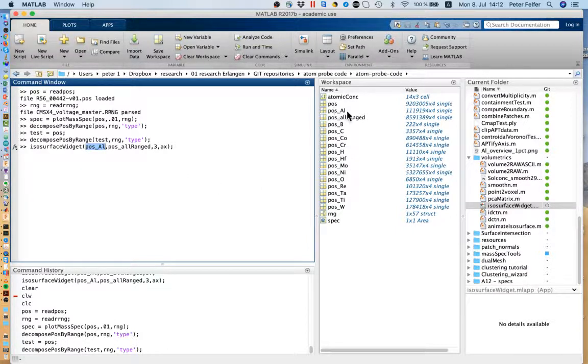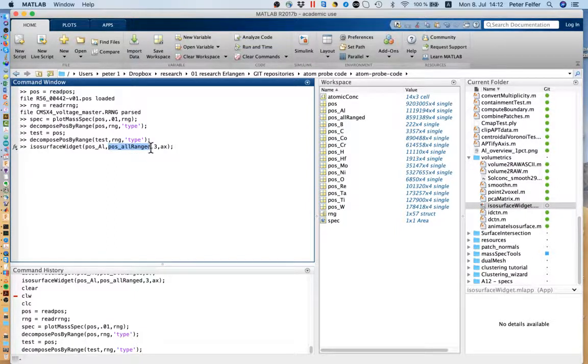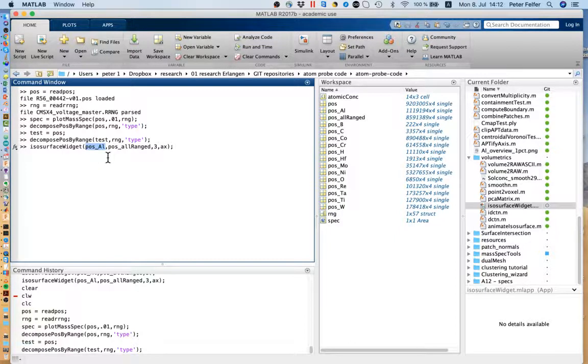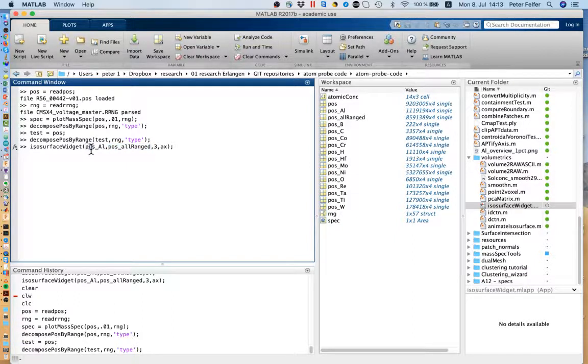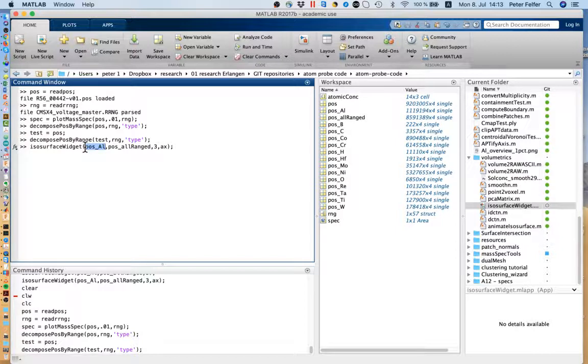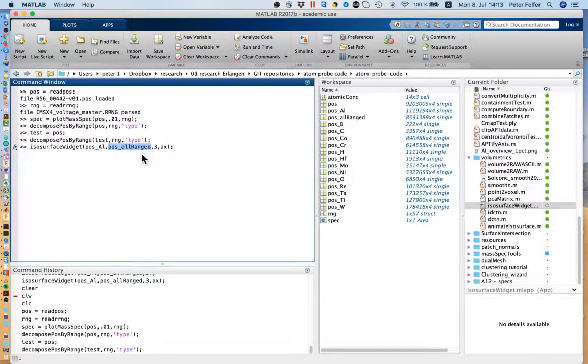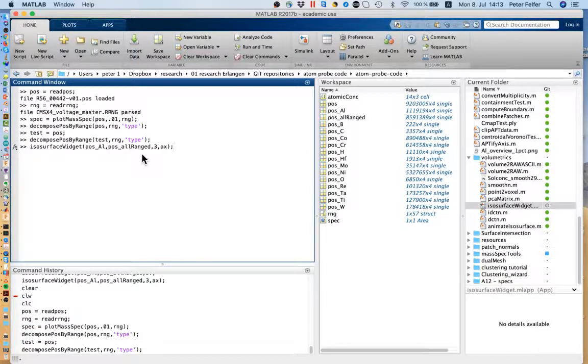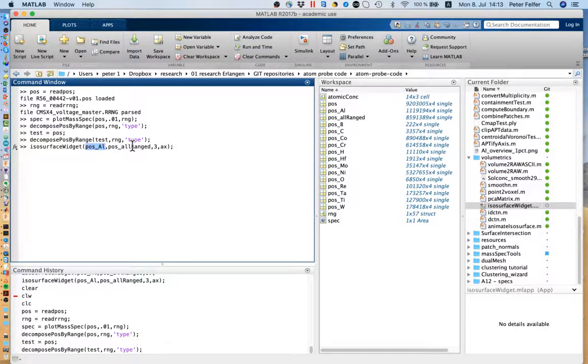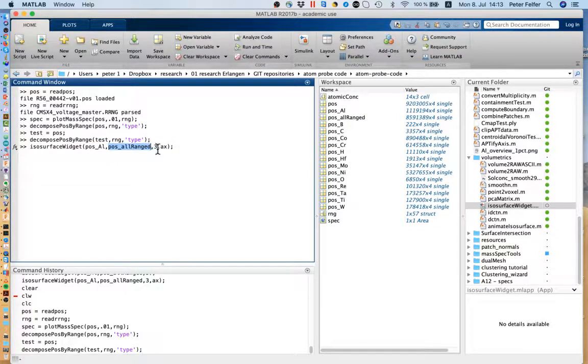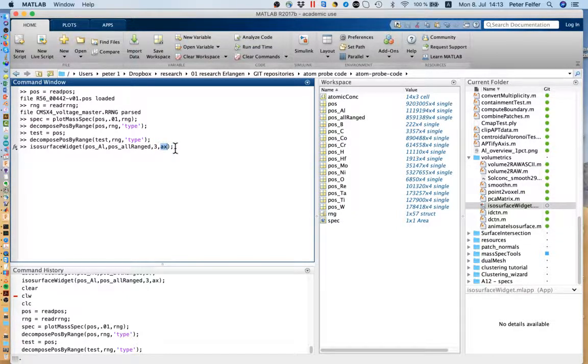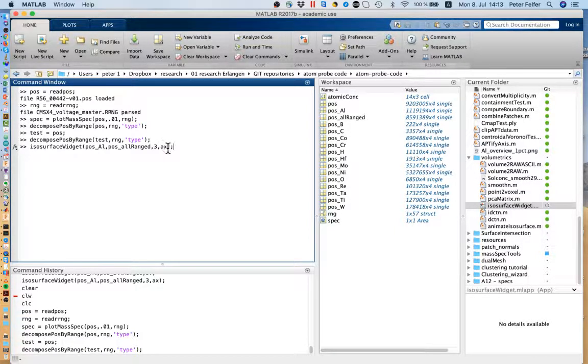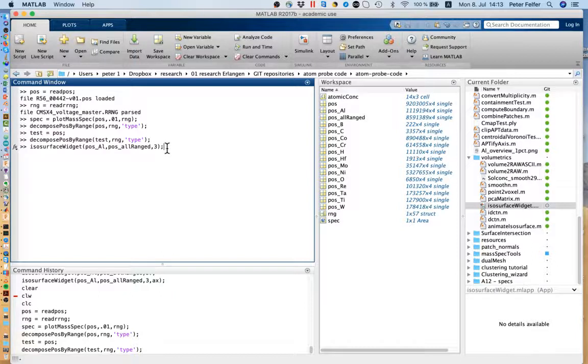Essentially a concentration field is number of atoms of a certain species of interest divided by number of atoms of another species. Or if you want a percentage, you could go, maybe if you want aluminum and nickel, you could go POS aluminum together with POS nickel divided by all range. But maybe you want to have stoichiometry isosurfaces and things like that. So this is the numerator and this is the denominator. Then we have the voxel size in nanometers, they are isotropic voxels. You can also give non-isotropic voxels. Then we have ax, and ax is the axis it will plot it into. For now I don't have one where I want to plot it into, so I can remove that and it will pop up with its own figure.